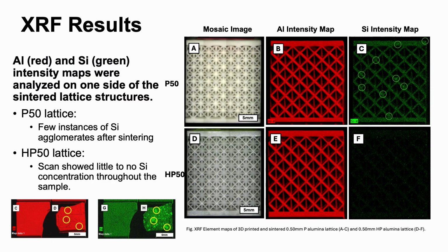So we did an X-ray fluorescence analysis of the sintered lattice structures to see if the silicon migration was apparent, as seen here in the bottom left-hand side. We found in another publication that after sintering there was actually silicon migration.